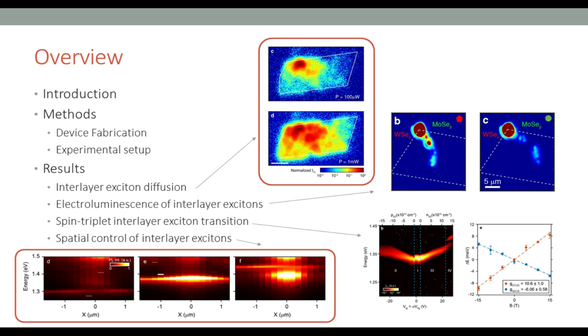Since the excitons have long lifetimes and they're permanent dipoles, they interact with each other and they can move across our sample. So when you pump with a higher power, you can see the entire sample lights up. You can generate electroluminescence, driving a current like a PN junction. We looked at the spatial control, so we make patterned gates and then control how these excitons move. And finally, we also explored some of the spin behavior of these excitons. But today I'll try to focus on the exciton diffusion and the spatial control of the interlayer excitons in the interest of time.